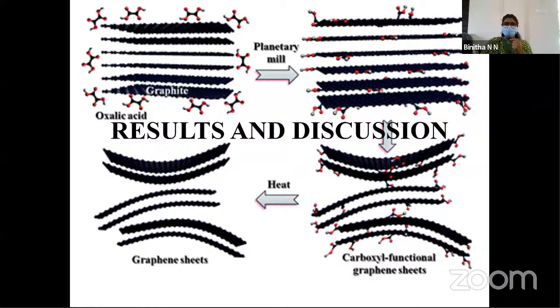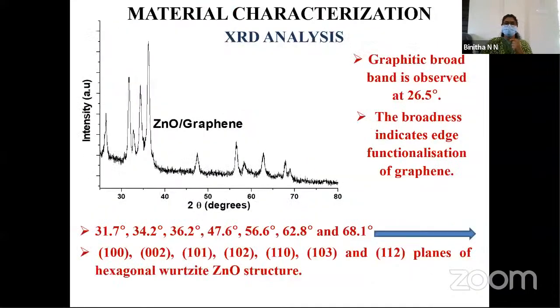About the results obtained and the discussions. The X-ray diffraction patterns indicate the peaks corresponding to zinc oxide. In addition, there is a broad band of graphene. The broadness of the band at around 26.5 degrees indicates there is a mild layer exfoliation only. If there is a drastic layer exfoliation, the peak will be shifted from 26 to around 10, 15, etc. So this indicates the graphene sheets are not fully functionalized, but there is somewhat functionalization, and we hope the functionalization is there in the edges.